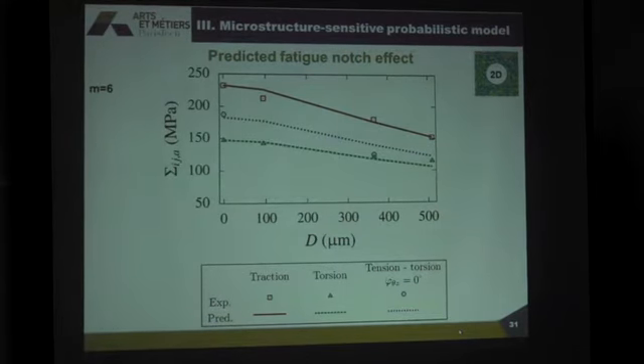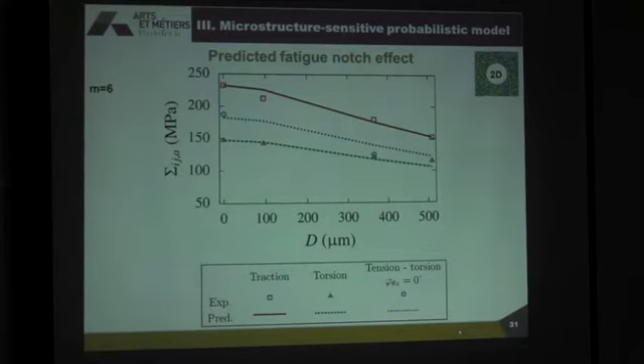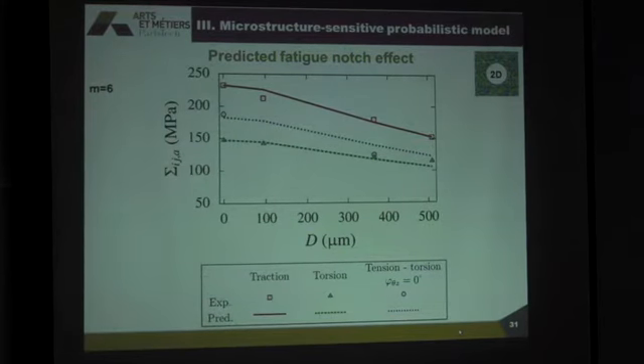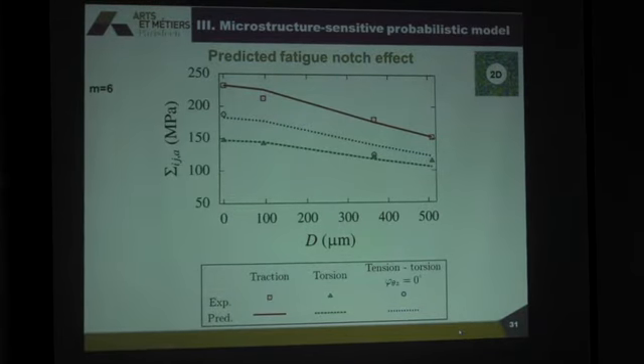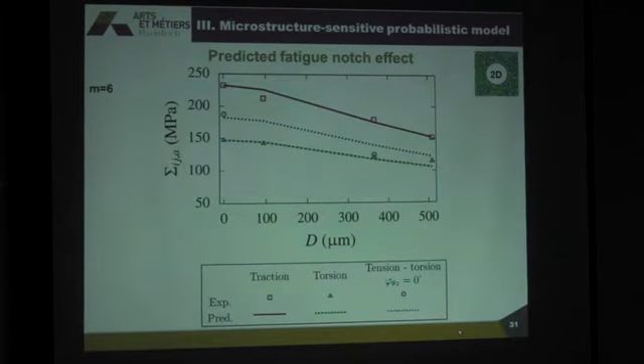What I try to show you here is that from the point of view of crack initiation, the Kitagawa effect is nothing else than the competition between the stress concentration due to the microstructure and the stress concentration due to the defect. It's only that.